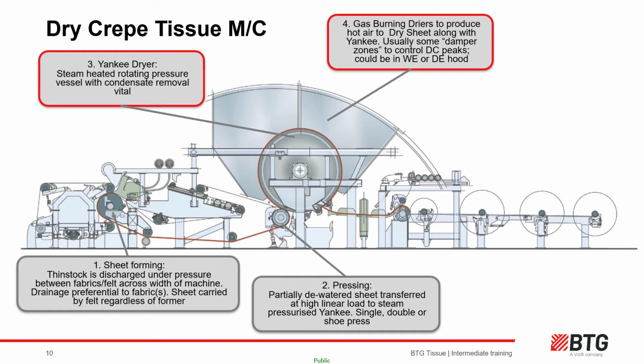After pressing, we have removed as much water by drainage and vacuum as we can, meaning the rest is removed by evaporation. This is the most expensive way to dewater, and after fibre is the second highest cost of production. Evaporative drying dries the sheet from 60% moisture to anywhere between 2 and 5% final moisture. There are two processes which combine to facilitate this drying process. Pressurised steam increases the Yankee surface temperature to about 80 to 90 degrees C to dry the sheet, and gas burners in the hood surrounding the Yankee heat outside.